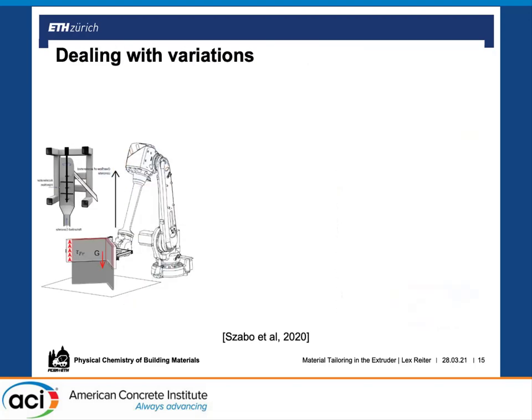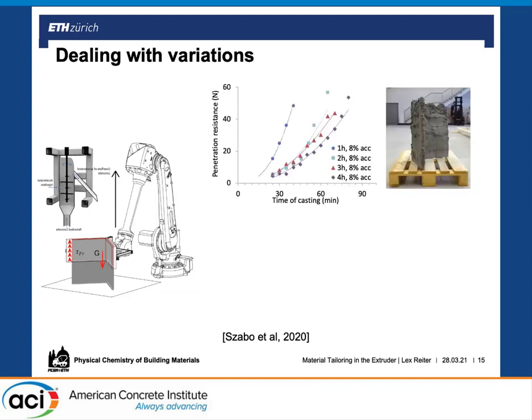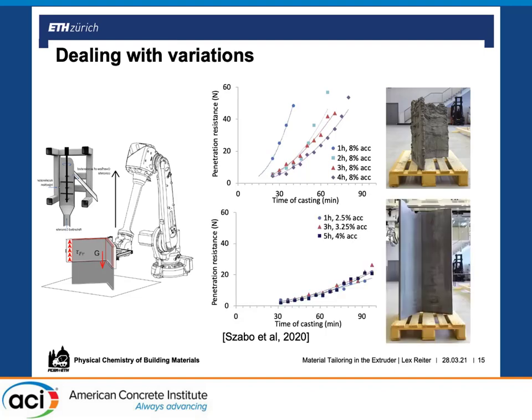However, not all accelerators are created equal, as shown in this example from Anna Szabo's thesis, where she was using an accelerator for slip forming. In her case, it mattered a lot at which time the accelerator was added to the system. So you get very different characteristics of the strength increase, and that was too much to deal with for her.